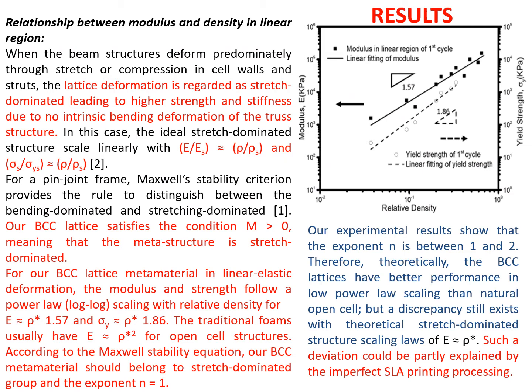As far as the relationship between modulus and density is concerned, the lattice deformation is regarded as stretch-dominated, leading to higher strength and stiffness due to no intrinsic bending deformation of the truss structure. In this case, the ideal stretch-dominated structure scales linearly with E over E_S equal to rho over rho_S, and sigma over sigma_YS approximately equal to rho over rho_S. Our BCC lattice satisfies the condition M is larger than 0, meaning that the metastructure is stretch-dominated.